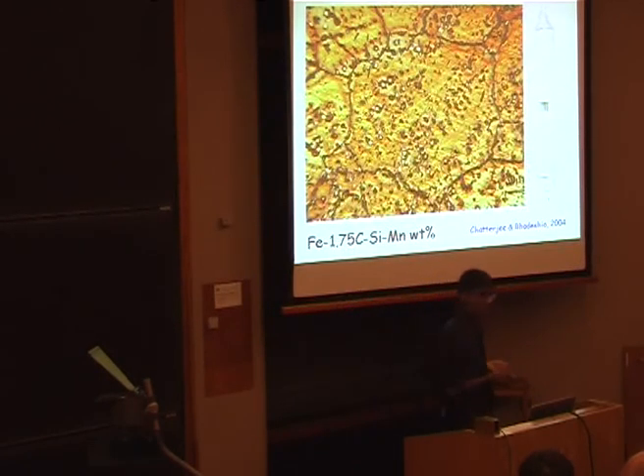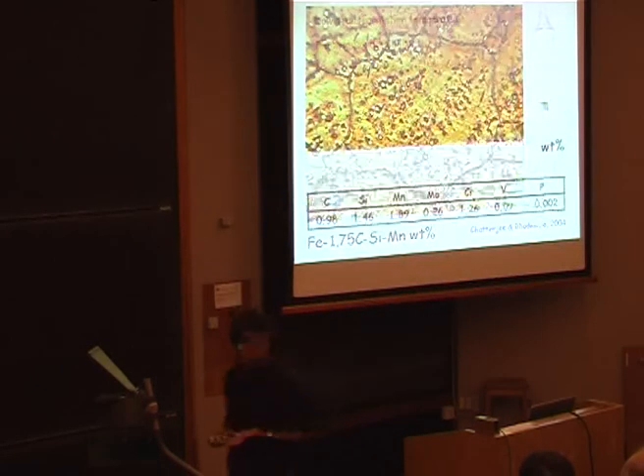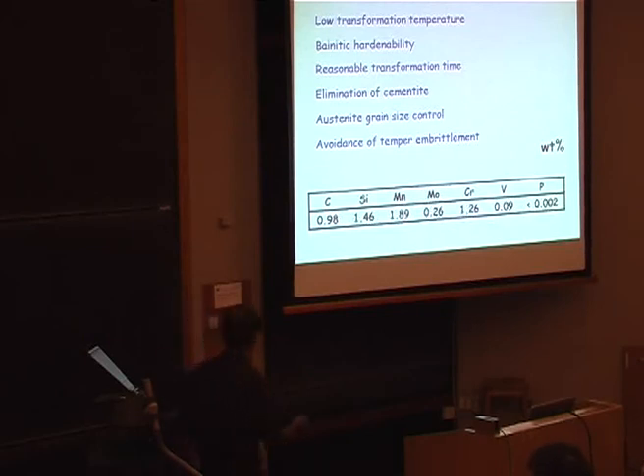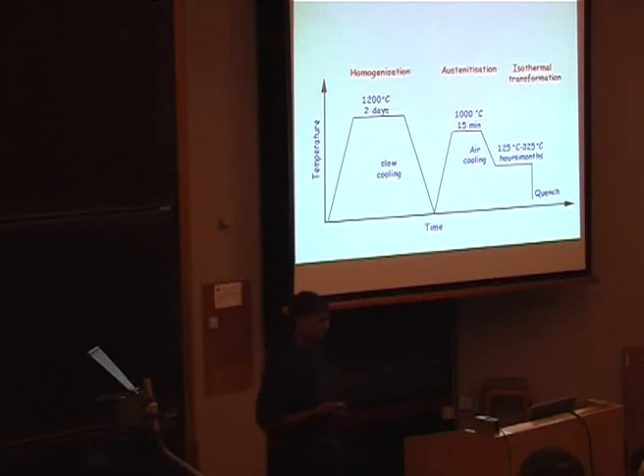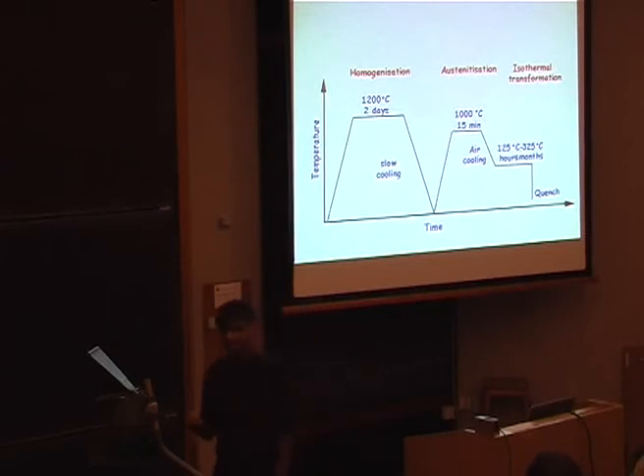But in the meantime, we have produced bainite at the lowest ever temperature, which is about 125 degrees, using this kind of an alloy. And I won't go into the details of all the different elements, but essentially, we've got about 1% carbon. And we transform it at a temperature as low as 125 degrees centigrade. And just to give you an idea of what that means, the diffusion distance of an iron atom at 200 degrees centigrade in 10 days is 10 to the minus 17 meters. So it's inconceivable that these atoms diffuse. And of course, that's not a problem because we are generating the crystal structure by a deformation, not by diffusion.